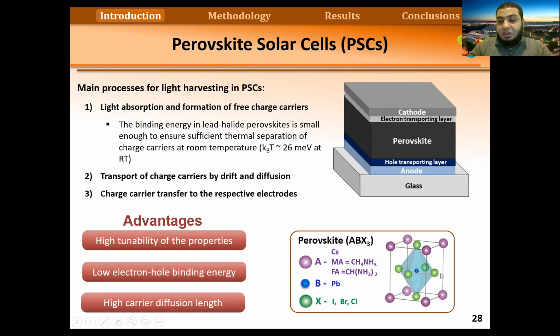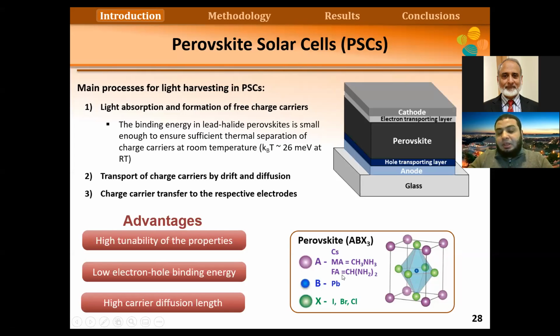The crystal structure here is a perovskite structure. It's named after a Russian mineralogist called Perovski, and he discovered this class of structures, and it can be different materials. But I'm focusing here mainly on the lead halide materials. In the A side, we can have different materials. We can have cesium, we can have methyl ammonium, we can have formamidinium. These materials can also be mixed. We can have cesium MA, cesium FA, and we use lead in the B side, and also we have a halide material in the X side.